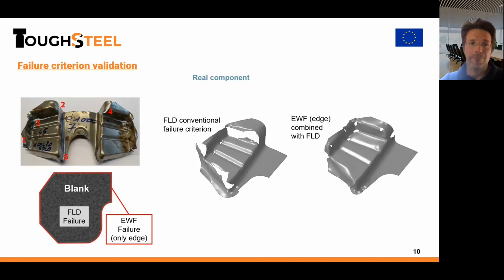The next one. This is another one of the real components from Fiat. And again, you can see the difference between using only the FLD and using the FLD together with our essential work of fracture criterion along the edges. With the FLD, the crack is very big in the middle of the component. And when we have the essential work of fracture, the crack starts in the edges and the failure is very different.